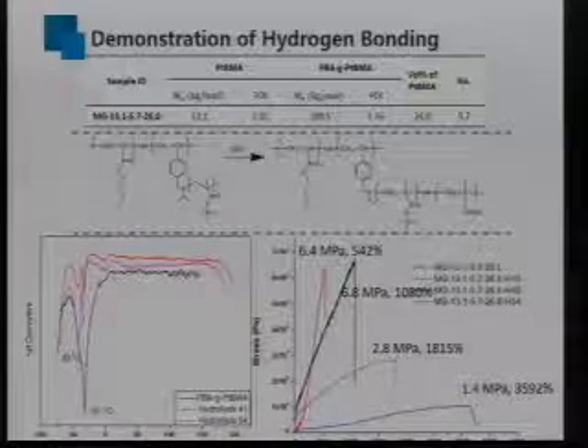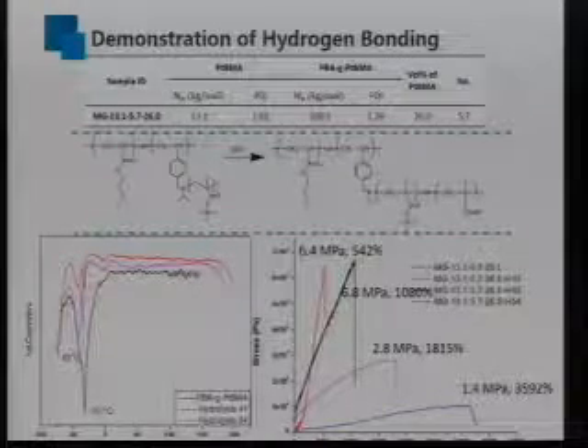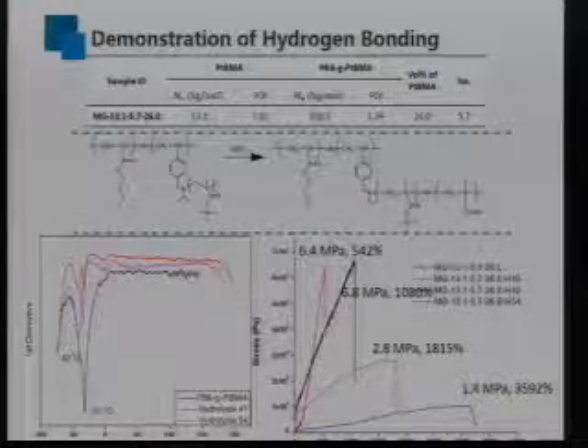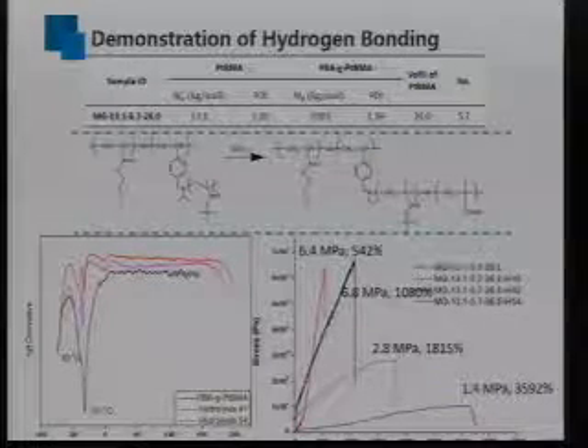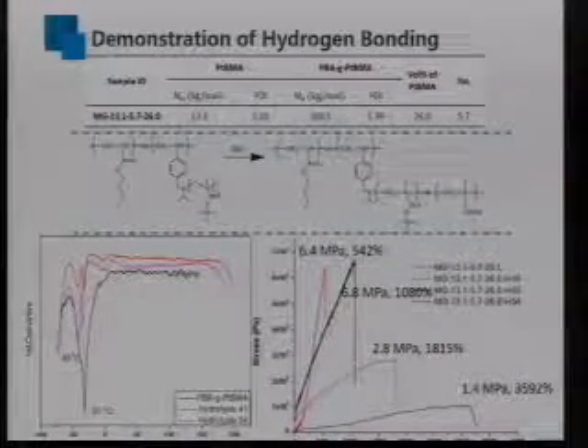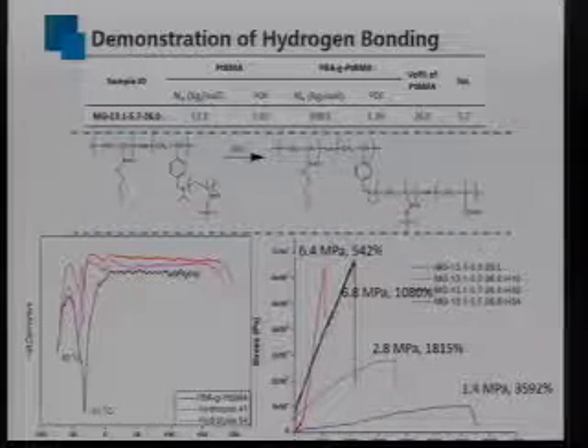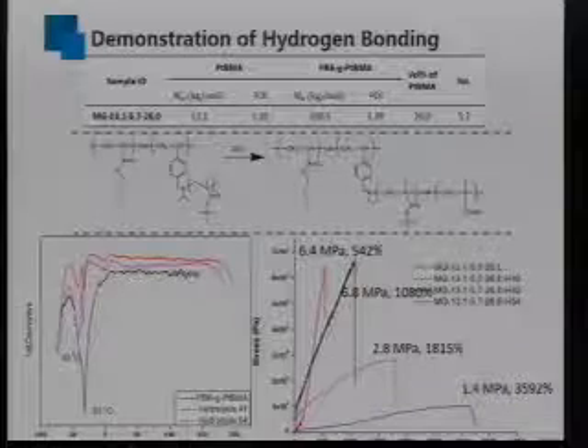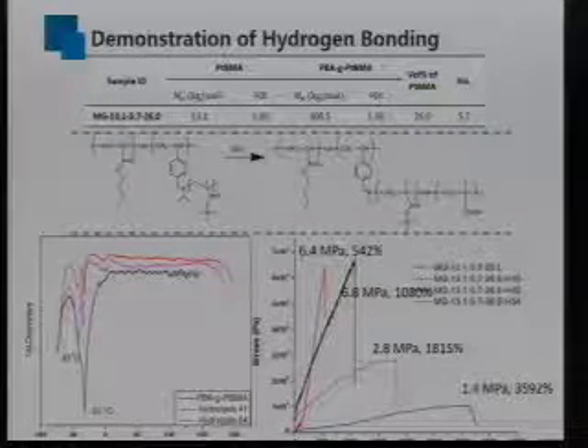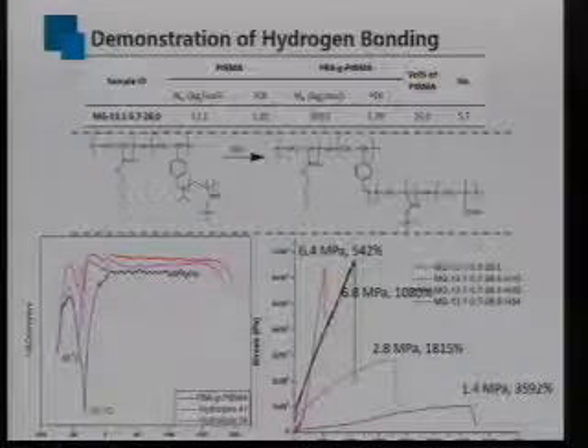And from the tensile test, when the hydrolysis degree reached 54%, it gave a mechanical strength as high as 6.4 megapascal, which is much higher than the original graft copolymer with only 1.4 megapascal, with the elongation still higher than 500%. When the hydrolysis degree is 42%, the mechanical strength is 6.8 megapascal, with the elongation higher than 1,000%. Even with a very slight hydrolysis of around 16%, the material still shows a 2 times increase of the mechanical strength, with the elongation higher than 1800%, for which we can still call it a superelastomer.